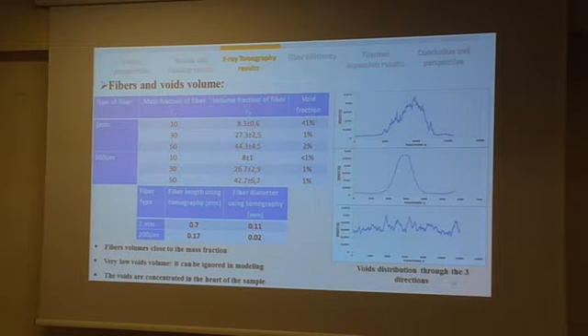So, using also a 3D model of the voids distribution, we were able to plot the voids distribution in 3 directions: direction X, Y, and Z. And we noticed that the voids are located in the center of the sample, and it's almost constant through the Z direction. And we were able also to measure the real length of fiber and the diameter of fiber and the volumic fraction of fiber and the voids in all the samples. So, with the help of X-ray tomography, we were able to have many parameters like volumic fraction of fiber and voids, fiber distribution and void distribution, also fiber length and diameters.